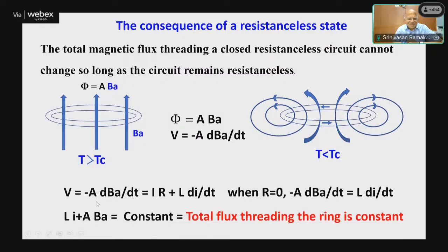You can put in this equation: V is minus A dB/dt, and that is current I times resistance R plus L dI/dt. Very simple equation. And when R is equal to 0, then these two become equal. Then you will see that L times I, the current, plus A times B is constant, where A is the cross-sectional area and B is the applied field. So the total flux threading the ring below Tc is always constant if it is a resistanceless state.